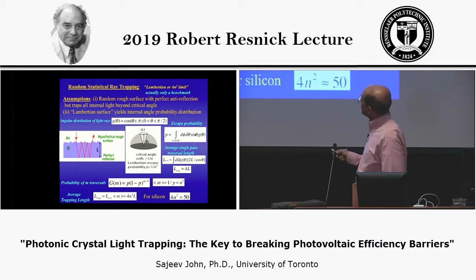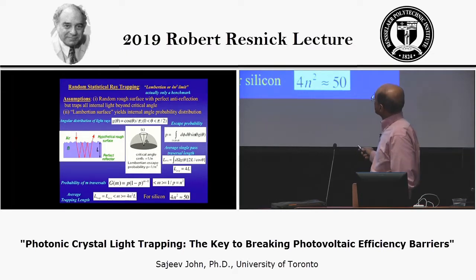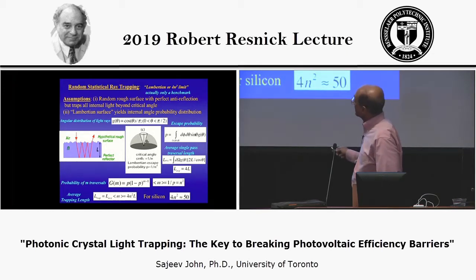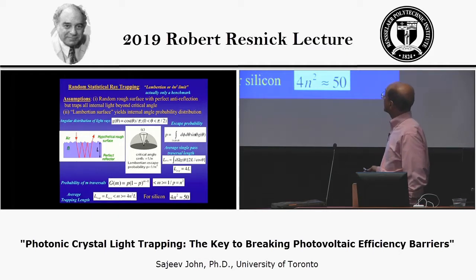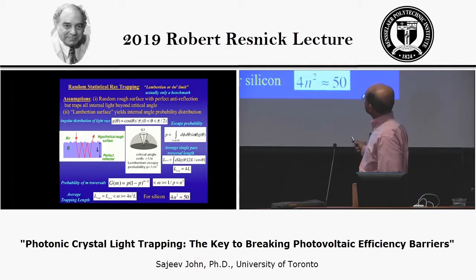The Lambertian surface is one that is assumed to deflect rays coming in, say, at normal incidence by a distribution of angles given by the cosine of the angle relative to the normal. And as you know from simple first-year physics optics, if the angle is greater than some critical angle defined by 1 over the refractive index, you'll get this phenomenon of total internal reflection. So let's suppose that we have a certain number of rays coming in and they bounce off at random angles, but defined by this distribution function. The probability that the light would escape is defined by it lying inside this cone.